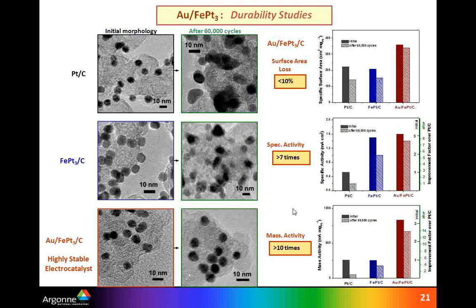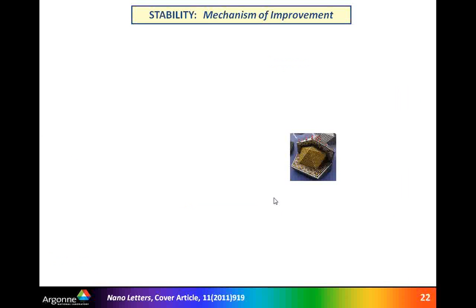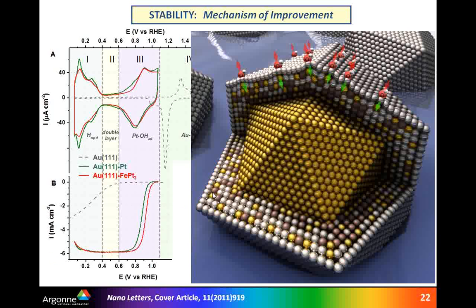So here is the summary of what was obtained after careful electrochemical studies. So first two lines, they show how platinum and platinum bimetallic particles would behave after extensive cycling. So there's a huge change in morphology, and also all of that affects loss in surface area and loss in specific activity. However, for those ternary alloys, we couldn't see any change in morphology, and the final outcome was the fact that mass activity was more than 10 times higher because there was no loss in surface area. And also we were able to gain substantially in specific activity. But what is intriguing is explanation of the mechanism of improvement.